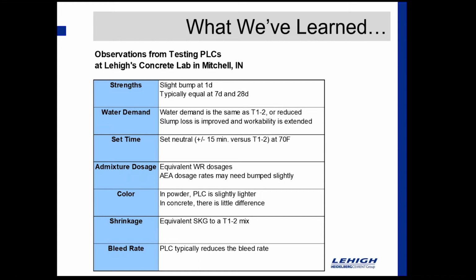Admixture dosages in terms of water reducer, that's been almost 1-to-1 straight up across the board. Air entrainment, because of the fineness of the PLC, you might need another quarter to half ounce, maybe something like that, of the air entrainer dosage rate. That may need bumped slightly.